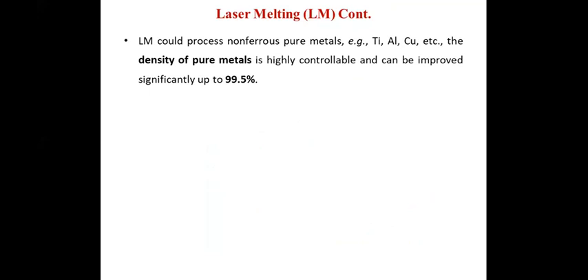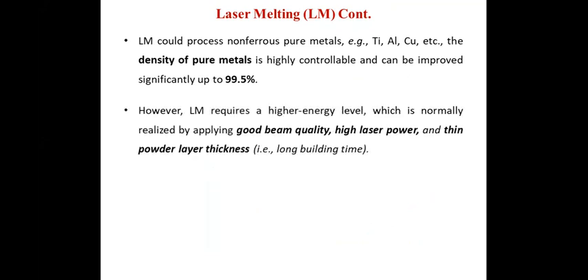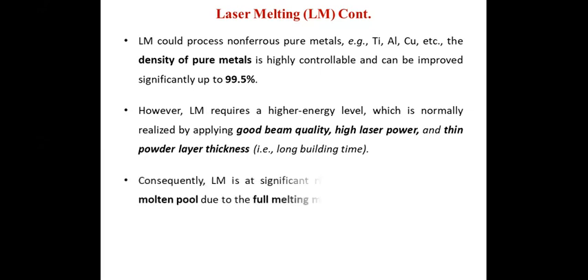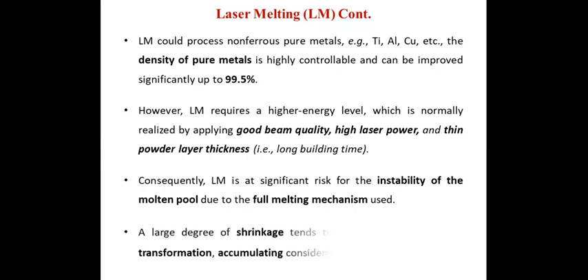Laser melting could process non-ferrous pure metals as well, such as titanium, aluminum, and so on. The density of pure metal is highly controllable and can be improved significantly up to 99.5%. However, laser melting requires a high energy level, which is normally realized by applying good beam quality, high laser power and thin powder layer thickness, which increases the building time. Consequently, laser melting is at significant risk of instability of the molten pool due to the full melting mechanism used.